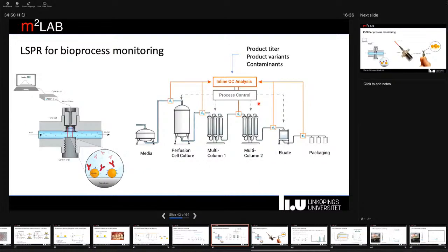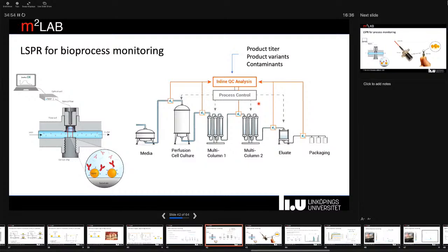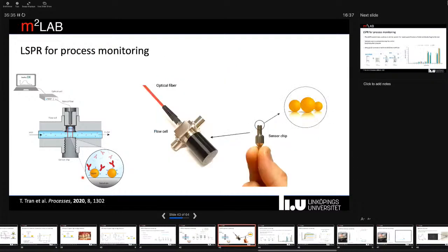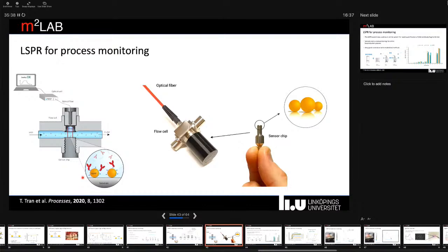So our ambition here is to facilitate work to intensify bioproduction by enabling inline quality control and detection of, for example, product titer, product variants, or contaminants. And we do this by using sensors similar to what you see in this illustration here. So a flow cell, very simple, combined with an optical fiber that's connecting to a light source and a detector. And then we have a removable sensor chip that is functionalized with particles. And it looks like this. So stainless steel flow cell, inlet, outlet, and optical fiber. And in here you have the sensor chip.